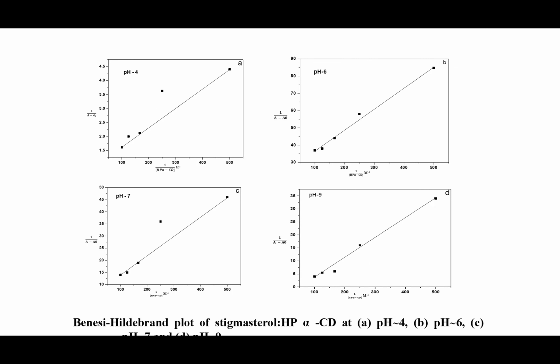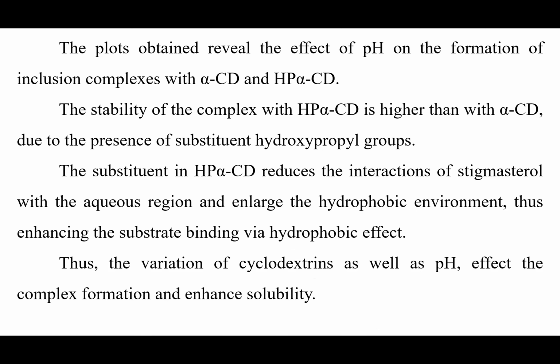So this is the plot obtained for the HP alpha CD complexes at different pH. Here also we get a straight line. From the straight line we calculate the slope value and calculate the binding constants. So the stability of the complex with HP alpha CD is higher. When we compare these binding constants, HP alpha CD is higher than alpha CD because of the presence of the substituted hydroxypropyl groups in HP alpha CD. The substituent in HP alpha CD reduces the interaction with the aqueous region and enlarges the hydrophobic environment, enhancing the substrate binding via hydrophobic effect.